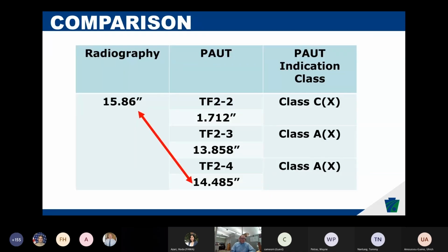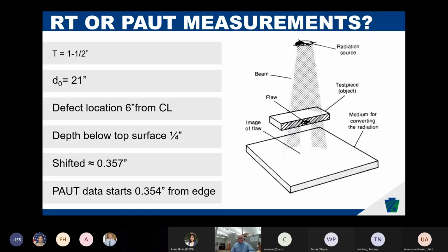So looking at the numbers a little bit, right? How well did they actually compare? So you have to do a little bit of interpretation of the 4 different phased array scanning files in this case. Where did the indication actually start? Where did it actually end? And come up with the actual length of the indication. In this case, it was all captured in that scanning file 4 index offset. And you might say to yourself, well, there's almost a 1.5 inch difference in discontinuity length between radiography and phased array. So did phased array miss a significant amount of the indication? And the answer to that is maybe not.